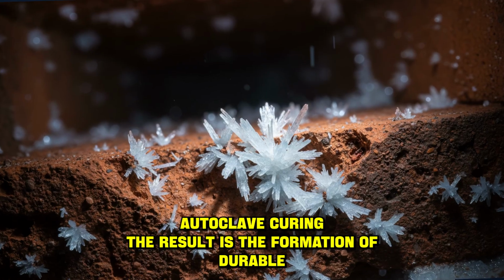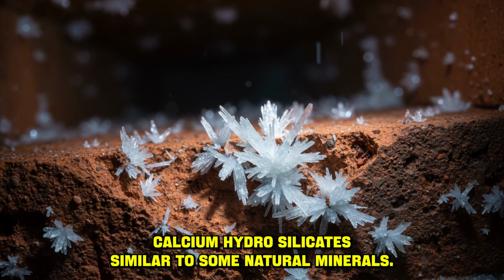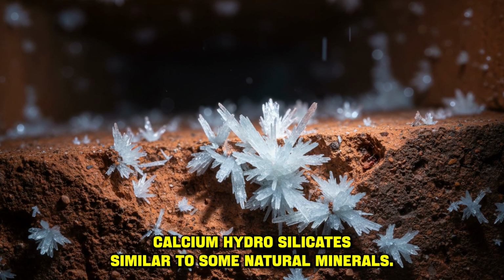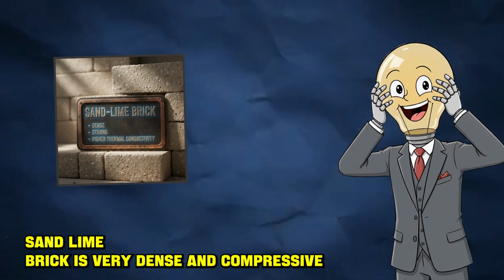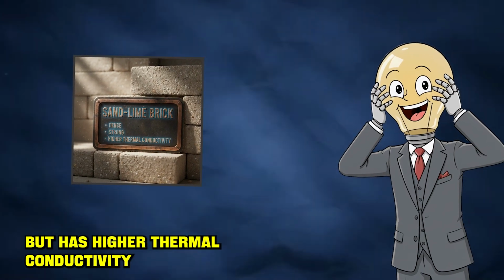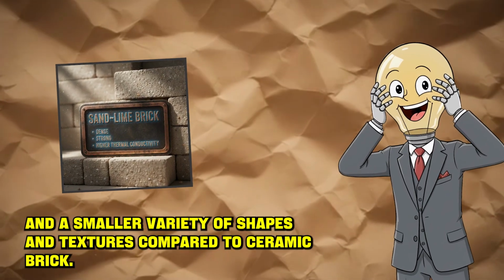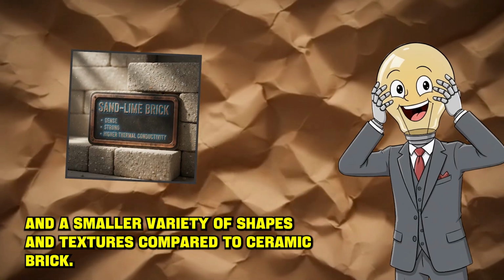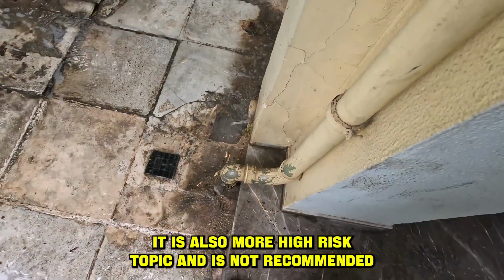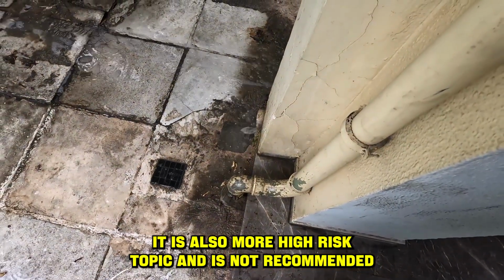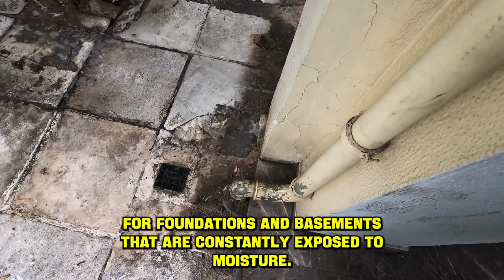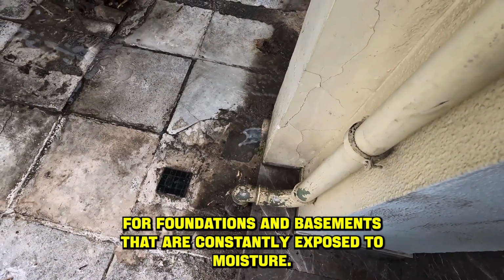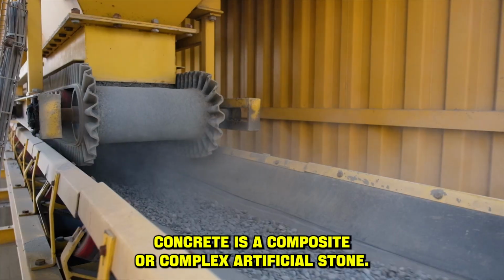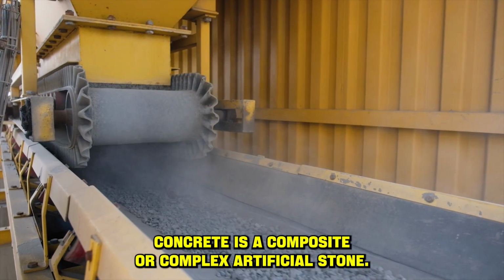The result is the formation of durable calcium hydrosilicates, similar to some natural minerals. Sand-lime brick is very dense and compressive, but has higher thermal conductivity and a smaller variety of shapes and textures compared to ceramic brick. It is also more hygroscopic and is not recommended for foundations and basements that are constantly exposed to moisture. Concrete is a composite or complex artificial stone.